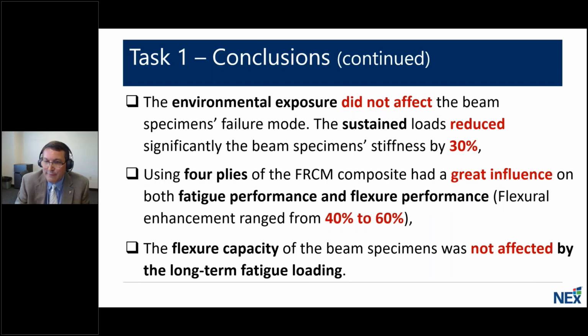Environmental exposure did not affect the beam's failure mode. The sustained loads reduced significantly the beam stiffness by as much as 30% as cracks formed in the matrix and softened the member. So it's not necessarily the crack development as much in the concrete beam, but in the matrix itself. Using 4-ply systems had a great influence on the fatigue performance and the flexural performance. So that enhancement, as mentioned, was 40 to 60%. And the flexural capacity was not affected by the long-term fatigue loading.